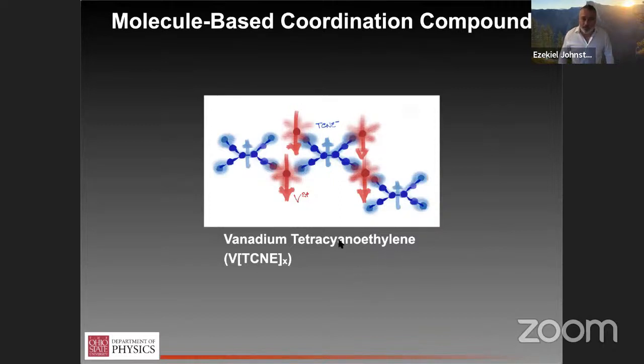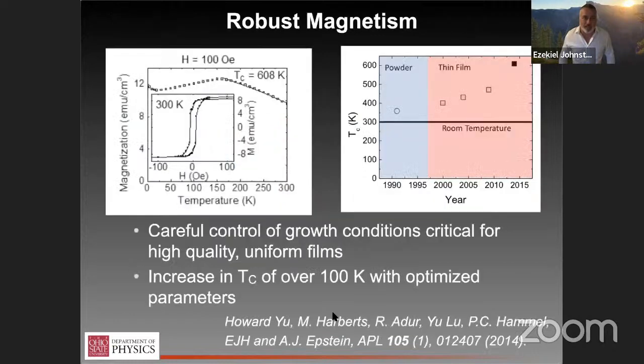So looking at this, though, this sort of violates all the basic rules of where one should look for a good magnet. The spins are relatively far away. The material is largely disordered. There's not long-range structural order. It's more polycrystalline at the borderline of being amorphous. So none of those things should give you confidence in the magnetic properties. And you might expect me to start talking about millikelvin temperatures or something to that effect. But in fact, quite surprisingly, this is an extremely robust ferromagnet. So the ordering temperature or Curie temperature for the material that we're producing currently is about 600 Kelvin.